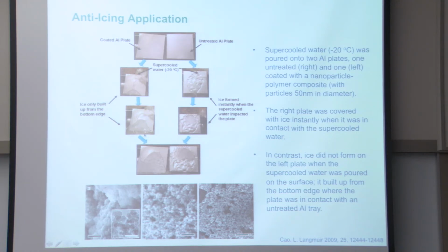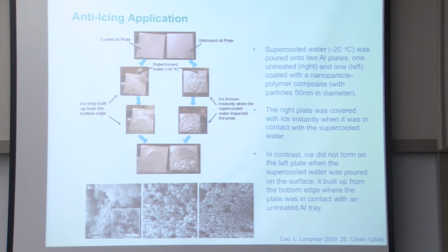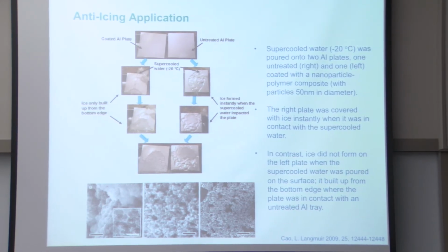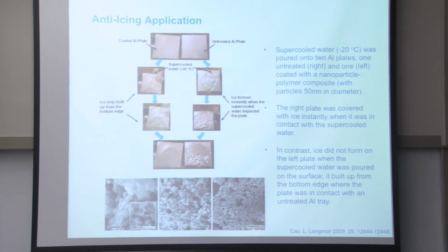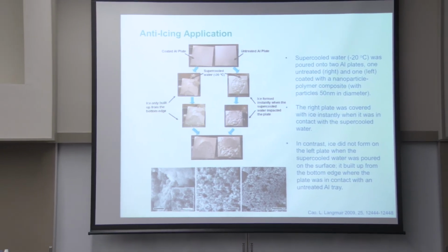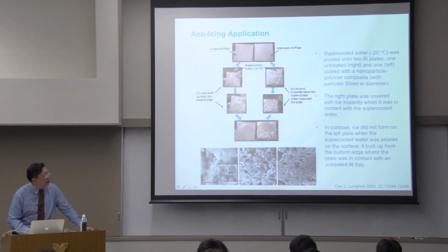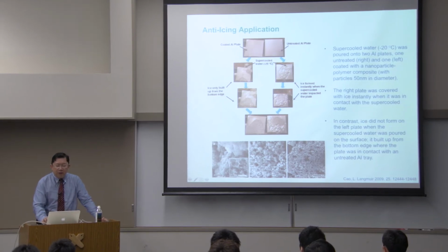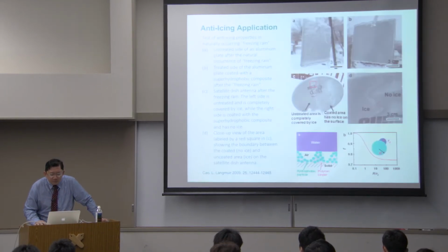In other words, when you first pour the supercooled water, it doesn't form ice. This is just one of the ways that has been used to demonstrate anti-icing application in such surfaces. If you examine the coated surface, you'll find this hierarchy of roughness that was coated on the aluminum plate.